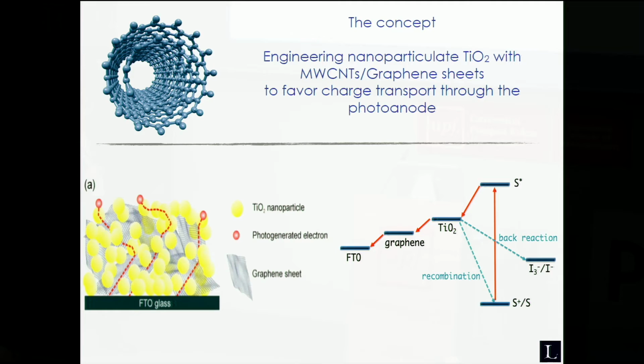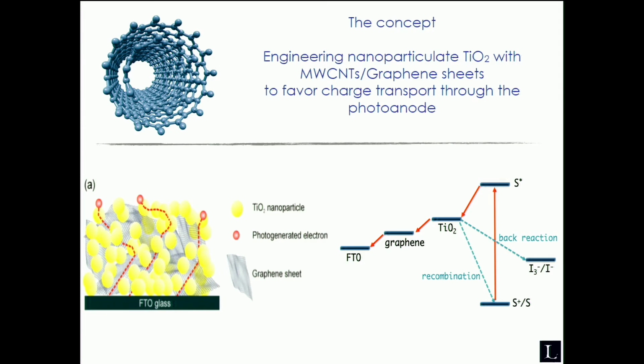We tried another way to increase electron collection in titanium oxide nanoparticles by integrating graphene nanosheets or carbon nanotubes, and in this process we tried to increase the conductivity of our layer and decrease the recombination processes.